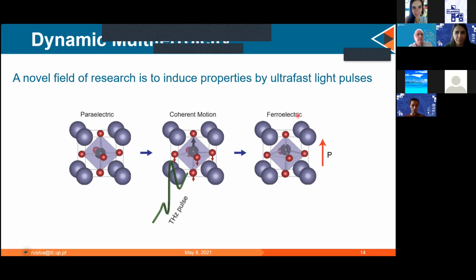Of course, this material is ferroelectric only for a short duration after this pulse arrives, which is in the picosecond scale. So you have, let's say, a transient ferroelectric phase coming from a paraelectric material. But if you want to have dynamic multiferroicity, you have to go further and you have to make magnetism also happen.